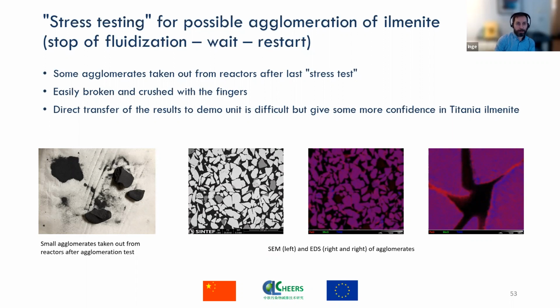And then we suddenly stopped the fluidization by pushing the emergency shutdown button, and we let the particle beds just lie still for up to 50 minutes. And then we tried to fluidize it again to see if it was only 2 big lumps, one in each reactor, but we managed to fluidize it every time. But when we emptied the reactor after the test, we found some agglomerates, but it was not very strong. It could easily be crushed with the fingers.